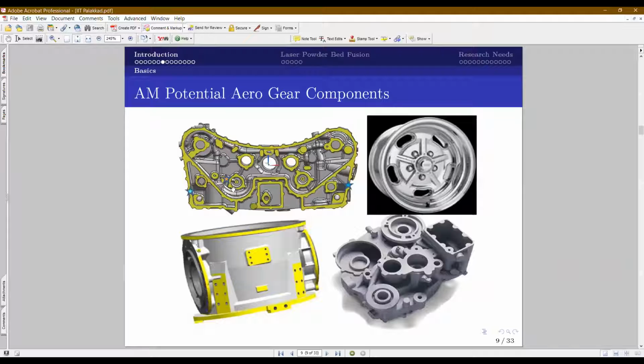The yield is 15%. The acceptance rate is very poor. Even if you make 10 components, only one component passes; the others fail at some of the regions. Either a dimension issue comes, or oil passage issues, or defects at the oil passage junctions. So these are the major reasons for the rejection of these gearbox casings.